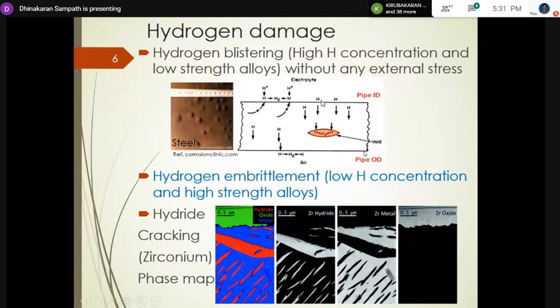It will not enter as H2, it will only enter as H, and it diffuses through the matrix. Whenever it hits interfaces or voids, it goes there and accumulates, and then due to thermodynamics, the atoms recombine and form hydrogen gas. These are very low strength alloys, so the hydrogen accumulates and creates a huge pressure, which exceeds the yield strength of the material, and at that point it leads to bulging or blistering. Blistering can later become a crack and then a catastrophic failure. And today's topic, hydrogen embrittlement, happens in high strength alloys at low concentration. In this case, we need external stress for the failure to happen, and we are going to see that in detail.